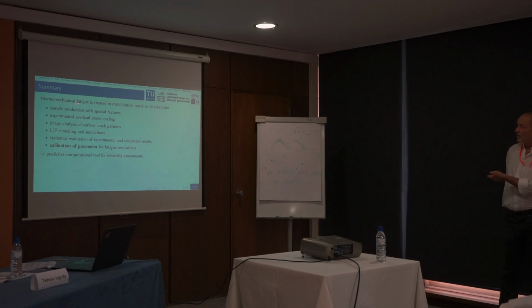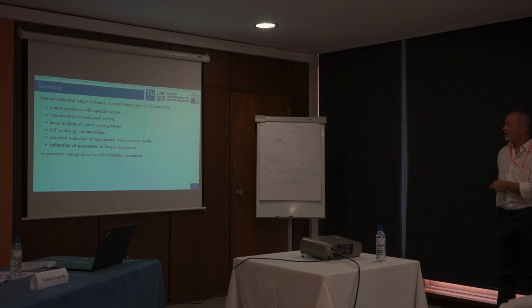Okay, thermomechanical fatigue on a metallization layer on a silicon substrate, as typically in microelectronics. Colleagues did sample production with special features on purpose. It was put to overload pulses in the experiments, and from the surface crack pattern image analysis was done.